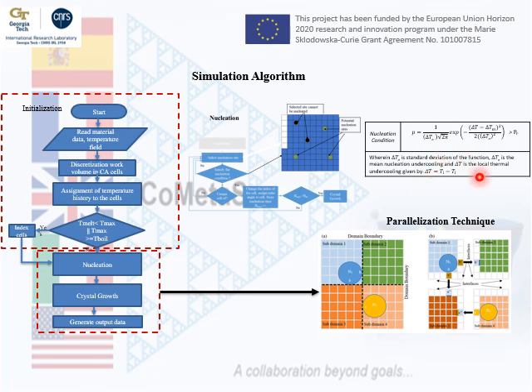Okay. In addition to that, our model was also implemented for parallel computer architecture. This is also to consider larger volumes of the representative volume element, and this simply allows us to increase the accuracy of the simulation model, right? Because with this, we can also decrease the cell size, and by decreasing the cell size, we can improve the resolution of the model, right? And this essentially means that we can consider all of the microstructural features that influence the mechanical properties of the material, right? So we can even decrease the cell size to the size of expected particles, for example, second phase particles.